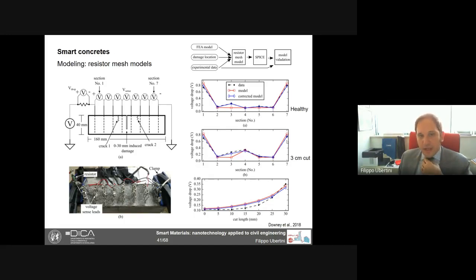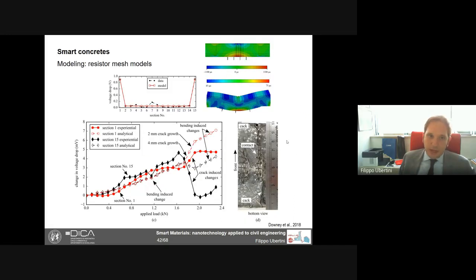I cannot enter into the details, but if you look at the bottom right, you see voltage drop as a function of the cut length, and you see that this increases with the cut length. And the model agrees with experiments with increasing values of the crack length. So we actually can track the severity of the damage.